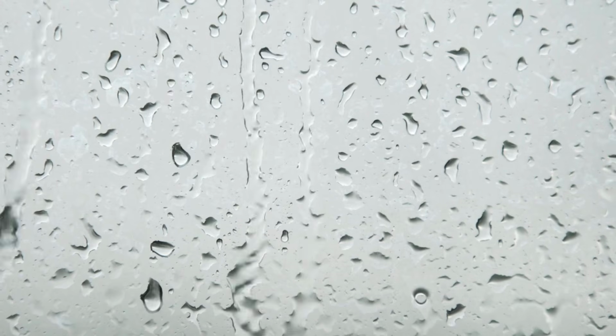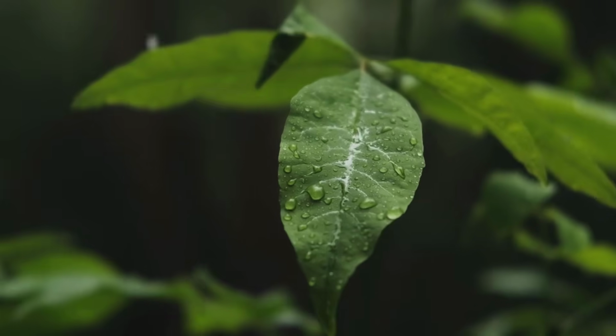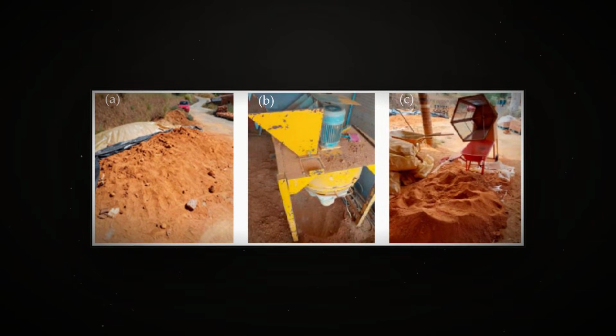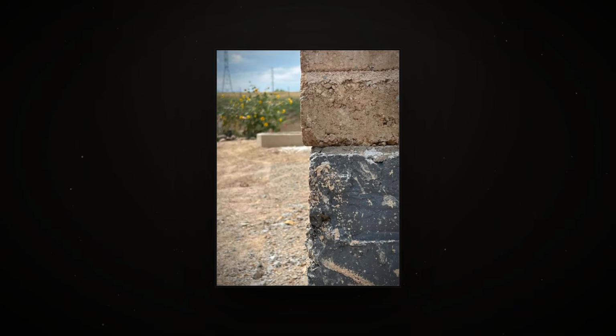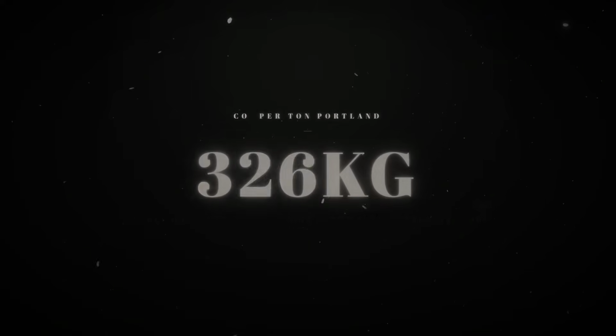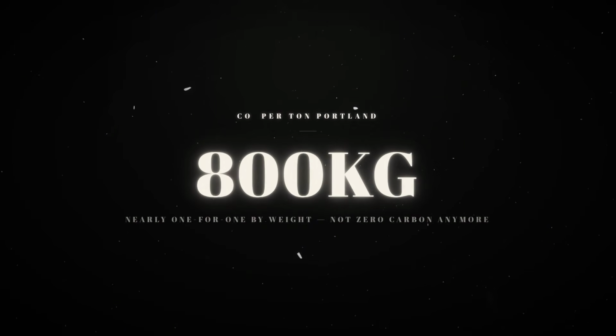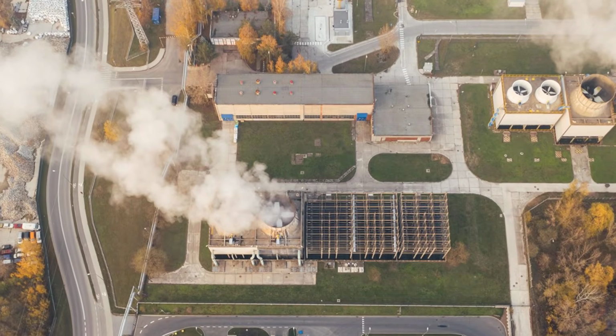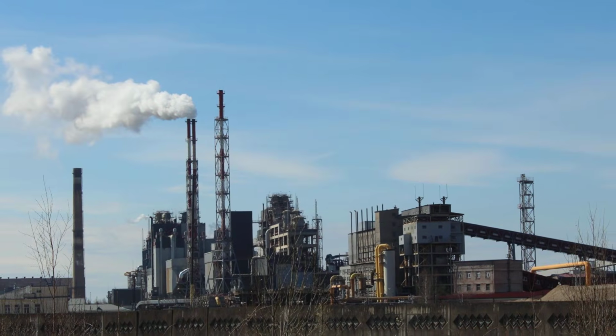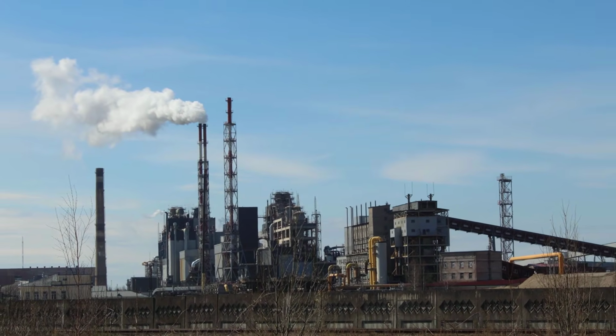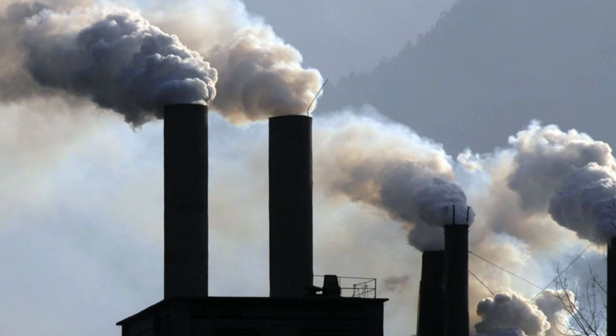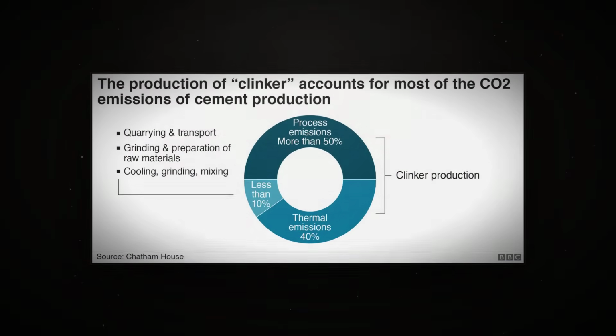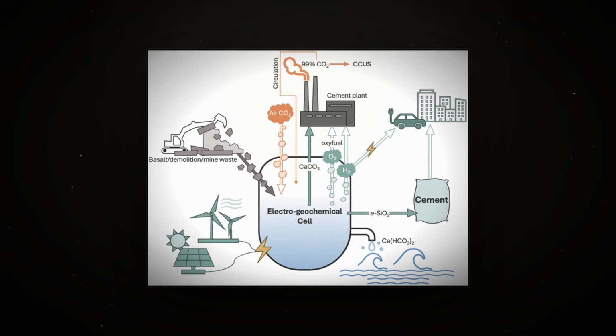Cement stabilization also dramatically improves moisture resistance. An unstabilized CEB can begin surface erosion in sustained rain. A stabilized block sheds water. That matters less in Tucson than in Portland, but it matters everywhere eventually. Here's the cost though. Portland cement is not free, and it is not clean. A ton of Portland releases roughly 800 kilograms of CO2 in production, almost 1-for-1 by weight. At 8% by volume across 3,000 blocks, you're no longer talking about a near-zero carbon wall system. You're talking about a low-carbon one.